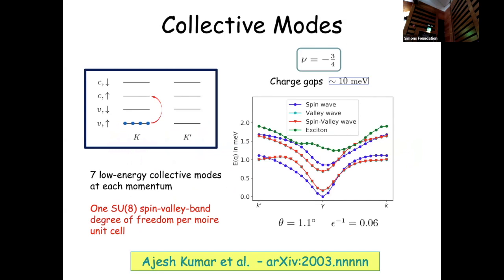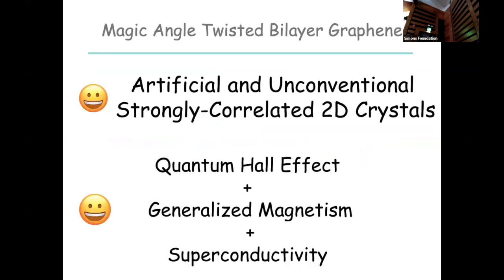which we've looked at quite a lot, it's quite hard to imagine that the Coulomb interaction can be made weaker than these essentially instantaneous optical phonon mediated interactions. And instead, I think these collective modes that exist, I believe, in the metallic state as well, as evidenced by the linear in T resistivity, are a very strong candidate for superconductivity. So let me stop there and leave you with that. So thank you very much. Thank you all.